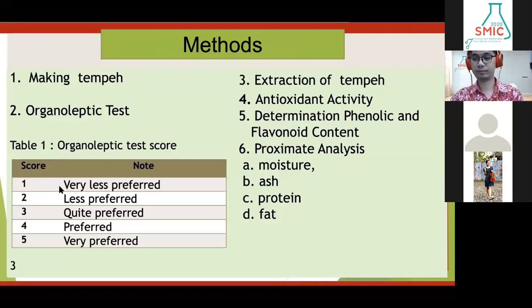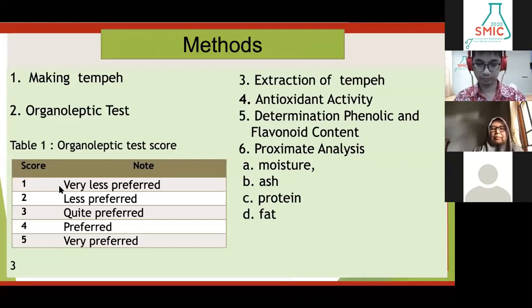Kidney bean tempeh extraction. Kidney bean tempeh was crushed by blender and we macerated it with 250 ml methanol PA and stored it for 24 hours. Then it was filtered to get the residue and filtrate. This procedure was done twice. The filtrate was concentrated using a rotary evaporator to obtain the kidney bean tempeh extract.